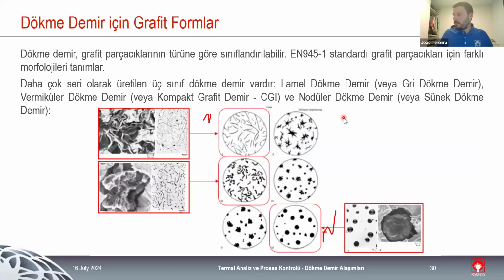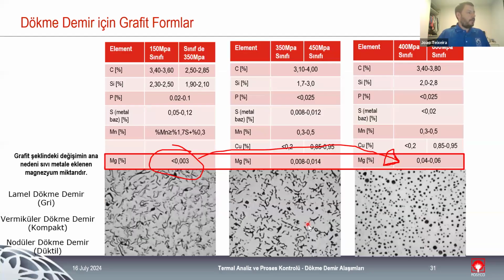nodularization. And the main goal of this step is to change the structure of the graphite. So we start with the gray structure, with the fine lines, worm-like structure of graphite. And each time we add a small amount of magnesium, we change the structure of the graphite, and we go from a worm-like structure to a nodule structure. We can see here that this is done by adding magnesium. So if you have a low percentage of magnesium, you have the gray cast iron that we know. And when we increase the magnesium rate, we change the structure of the graphite.